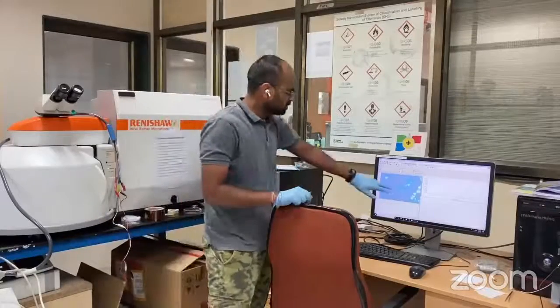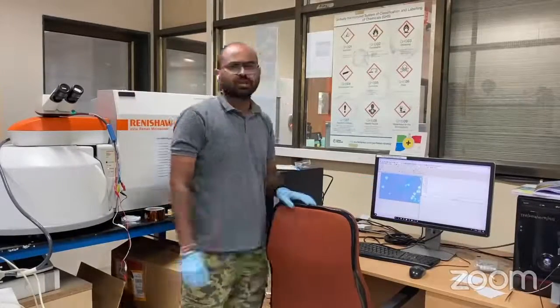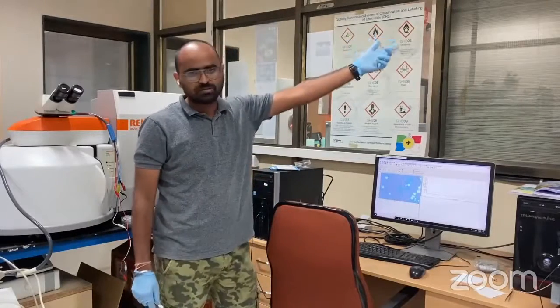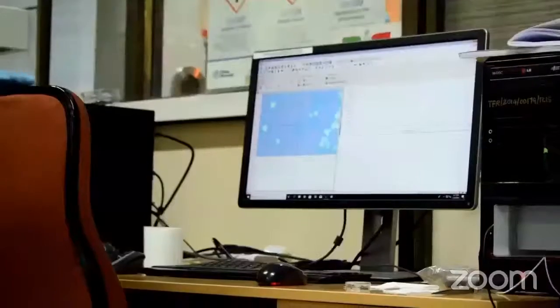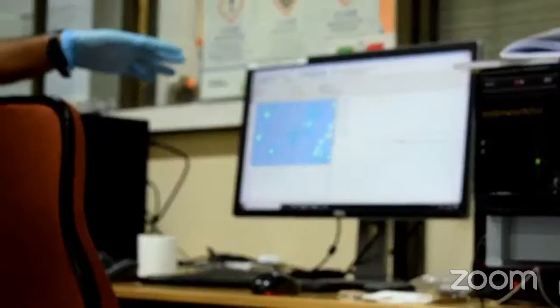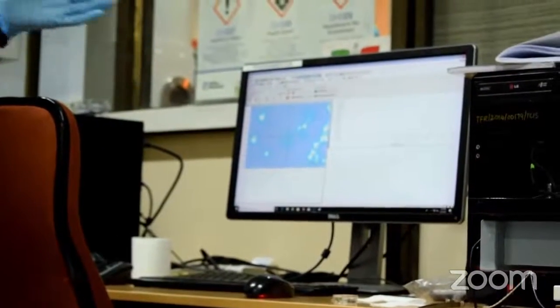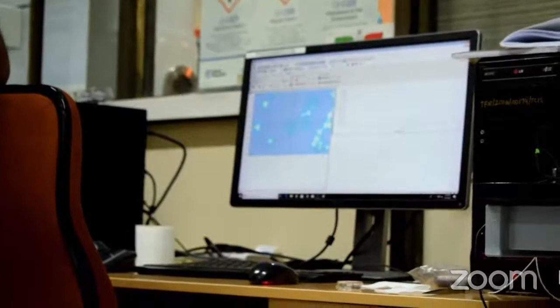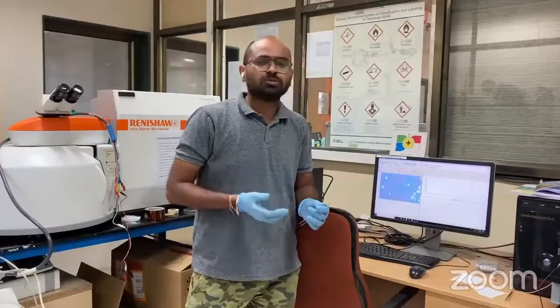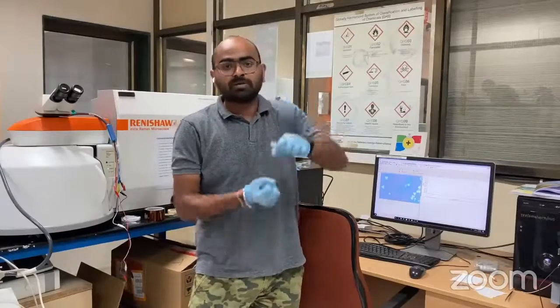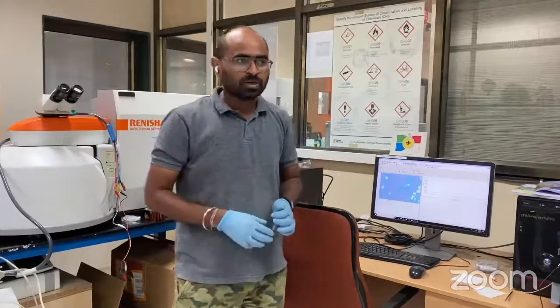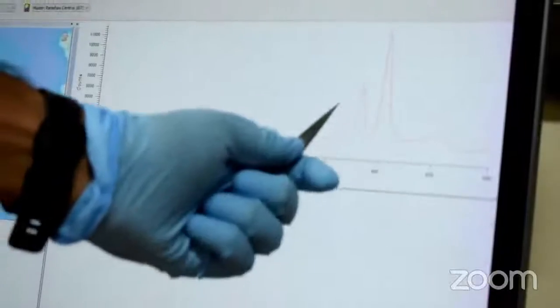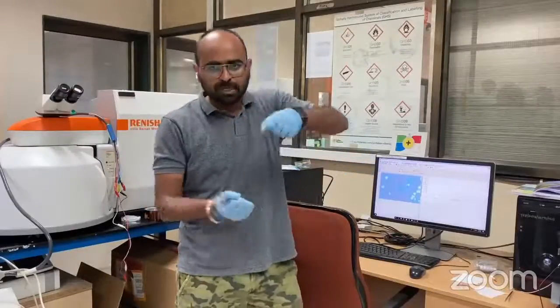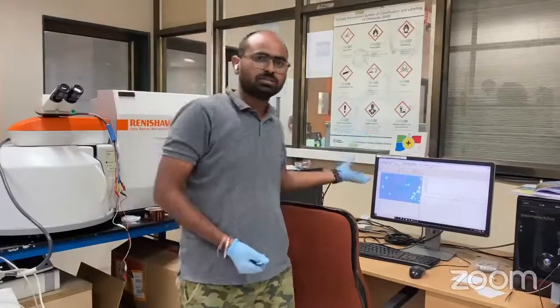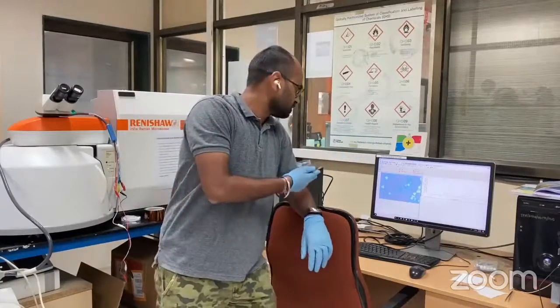As you can see in these morphologies, these are the monolayer triangles that we can grow with the help of chemical vapor deposition. Optically we cannot figure out whether it's a monolayer or not. To detect it, we usually use Raman spectroscopy. Raman spectroscopy tells you the energy of the vibration with which the atoms are moving. If it is a monolayer, you can see there are two peaks. These two peaks belong to MoS2. These are the in-plane and out-of-plane vibrations of the atoms in this system.